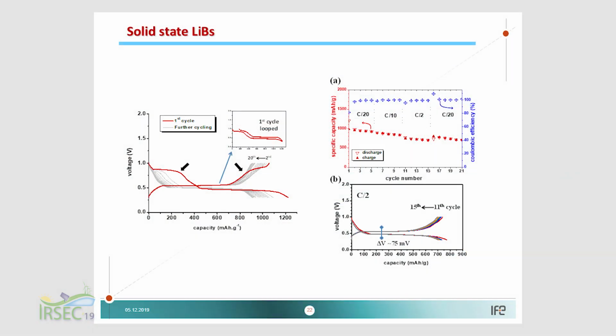The only thing we could notice here is a decrease of this plateau during cycling, without any decrease in the capacity. So it means that cobalt oxide still remains active, even though the plateau is disappearing. We know that cobalt oxide is undergoing some transformation. It has some dispersive effect in the material, which is also a good conversion type material.